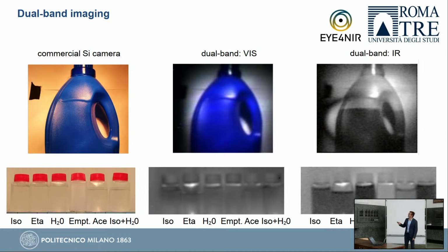So you can see this is a blue bottle imaged with a mobile phone silicon camera. So it's very nice. And this is the same image taken with our sensor, where the pixel size is much larger, okay? But basically the information content is the same. This is a blue bottle. Now, when you reverse the bias and take the same image in the infrared, what you see is that this plastic is transparent, as are many polymeric plastics, and the water inside the bottle is actually a strong absorber in the infrared. So you can look inside the bottle and tell whether it's empty or filled up.